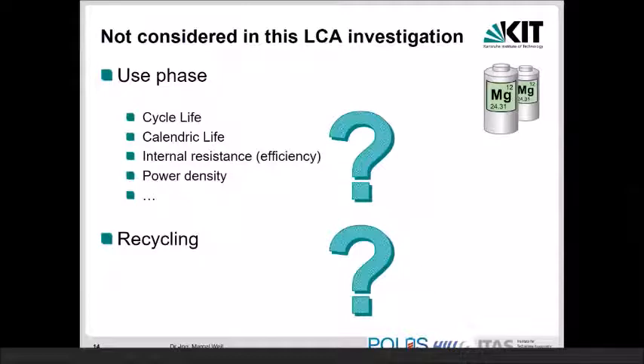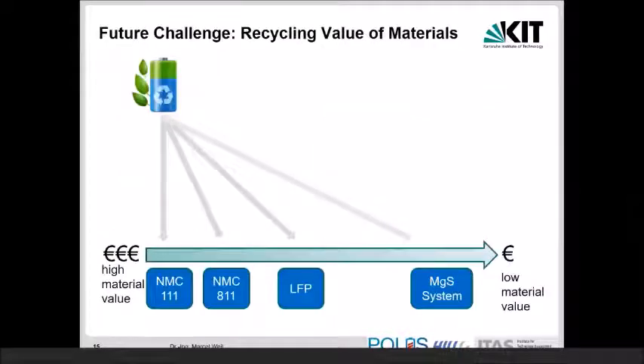Another point which is not included is, of course, recycling. I'd say the recycling of lithium-ion batteries is quite difficult. It costs a lot of energy or chemicals. And so there should be something different for all the post-lithium batteries. With the next graph, maybe I can stress this a little bit. If you see here the different values in the cells, NMC 111 has a lot of cobalt in it, and therefore the value is quite high. So if you recycle such a battery, you are quite lucky because you can get all the cobalt out of it, and also, of course, other materials like copper and nickel and manganese.